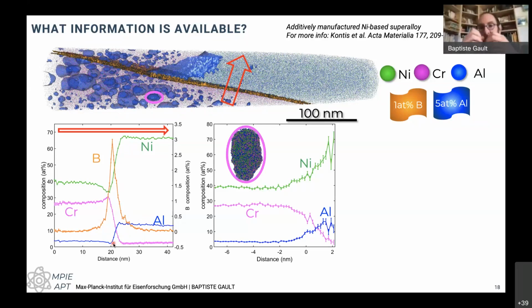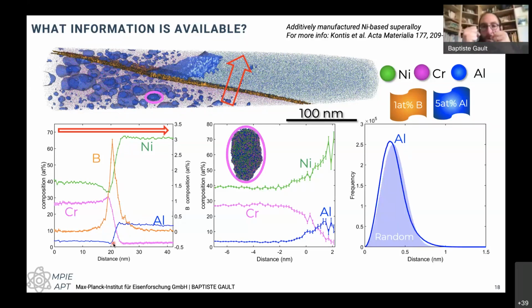And then because I have this assembly of points, I can also look at an aluminium atom and ask where the next aluminium atom is. Is this distance compatible with a random distribution, or is it not? If it's not, then it might indicate that there are tendencies for the aluminium to agglomerate, so maybe some clustering tendencies. In that case, it's an ordered phase, so it's probably a bit more complicated than this, but just to give you some hints of what we can get out of it.